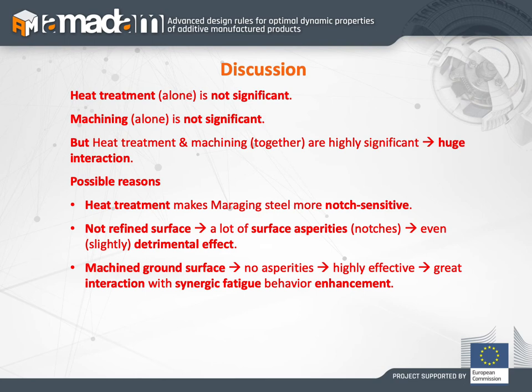We can explain this by two reasons. First, the heat treatment makes maraging steel more notch-sensitive. So after aging the material, if we apply the machining, we erase the surface that is notch-sensitive due to the fact that it has been subjected to the heat treatment. On the other hand, if we consider only the machining, we are not able to erase so many voids or so many defects on the surface that were previously erased by the micro shot peening, because we have to consider that the micro shot peening was applied to all the specimens.